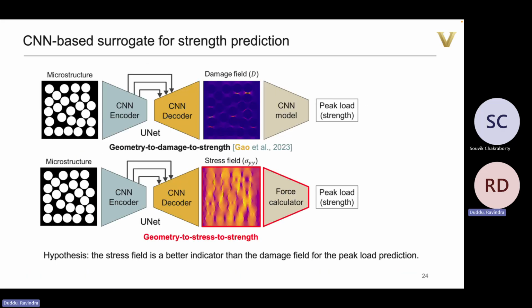So we did that, and then we also said, let's not do damage field, let's do a stress field. And for stress field, you know that if you integrate the stress on a horizontal line, you can calculate the force, and then you divide it by the distance, you get a traction, if you want traction. But you can just directly get the peak load by integrating along a horizontal, all the stress in the normal direction, in this case sigma yy, and you get the peak load, right? So you don't need another CNN model. In fact, in hindsight,